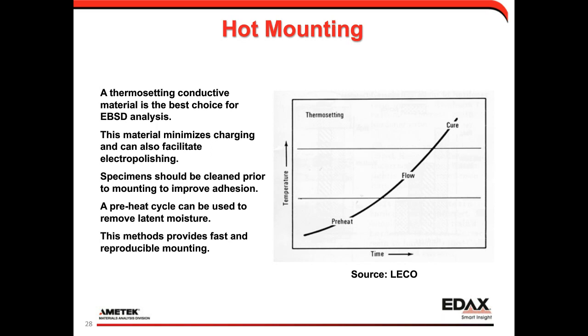The important things to note here is you really want to have a clean sample before you go. It helps to improve adhesion of the material to the sample. And it's fast and it's reproducible. I can put a sample in our hot mount press, and in about 10 minutes I have a sample that I can take to the subsequent step, compared to some curable epoxies that can take hours to multiple hours.